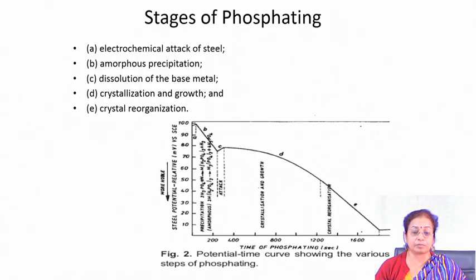So, when this phosphatization operation is carried out on the metallic surface, it offers significant corrosion resistance. If you see the stages of phosphatization, they are like this: electrochemical attack on the steel, then an increase in potential with the time of phosphating, and as you apply some more time, there will be an amorphous coating which does not have any crystal structure, then dissolution of the base metal, then again crystallization and growth of the phosphate layer, and finally crystal reorganization.